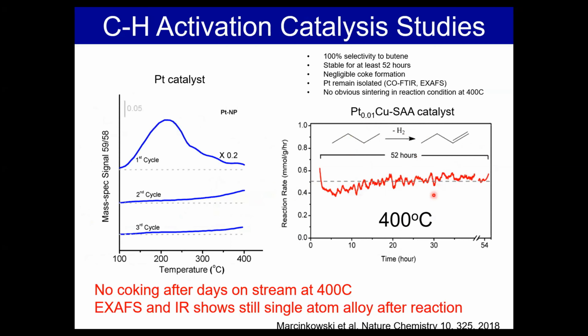Whereas the platinum catalyst is very active, but even after the first cycle, half an hour later, you've coked most of the sites and the activity dies off and you've covered up most of the sites. So this is a very interesting direction for CH activation, where the single platinum atom will lower that barrier significantly. But because the surface is mostly copper, you can keep your high selectivity, you don't coke, and you can also